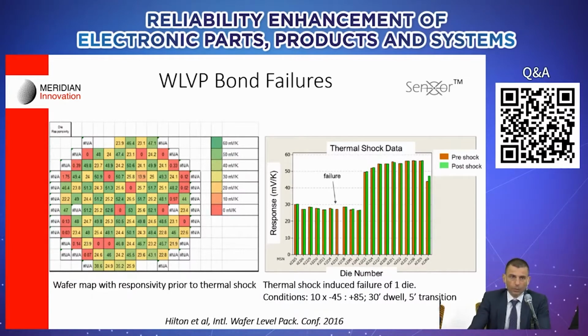And in this case, it is seen that after the thermal shock, at least one of these dies completely lost any sensitivity to heat, no response to heat basically. So that typically happens when the bond between the two dies is ruptured, or if there was a microcavity that was completely expanded during the thermal shock.